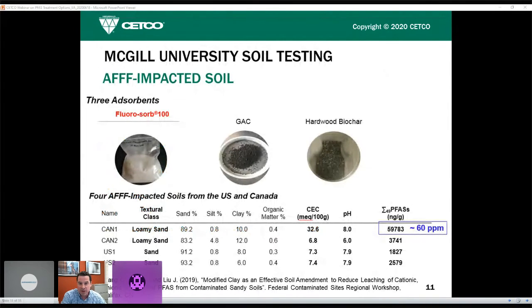So as Mike mentioned, we've been working with a few different universities. And this particular study was done at McGill University in Montreal. We were looking at the impact of FLUORO-SORB on treating AFFF impacted soils. We took multiple samples from a couple different sites, one in Canada and one in the US, and these were Air Force bases used by the military. You can see slight differences in the types of soils at the sites, and a big difference in the concentrations of PFAS in the soil, ranging from 60,000 nanograms per gram all the way down to 1,800 nanograms per gram. Next slide, please.